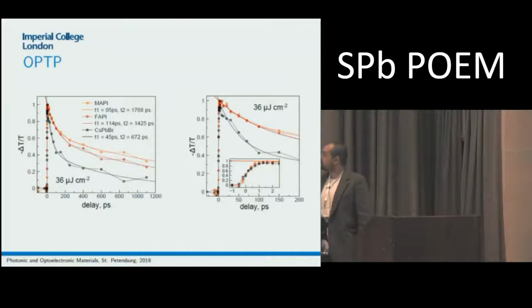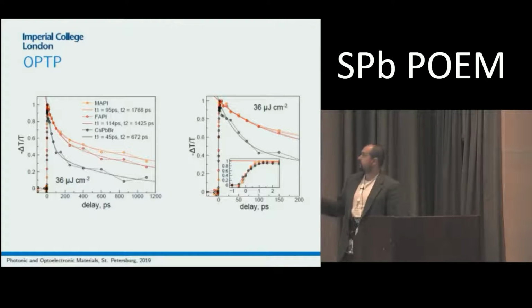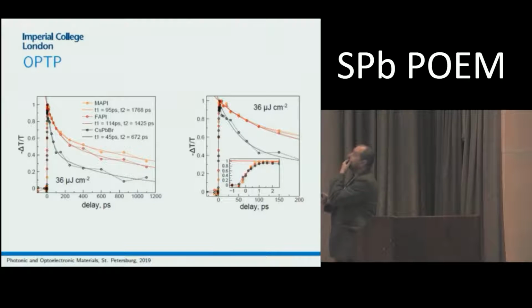We can see similar trends as we noticed in optical measurements, that cesium lead bromide reveals much faster relaxation times than MAPI and FAPI, the formamidinium lead iodide. And if we look at the earlier times, we can see that the build-up is quite similar for all of them.